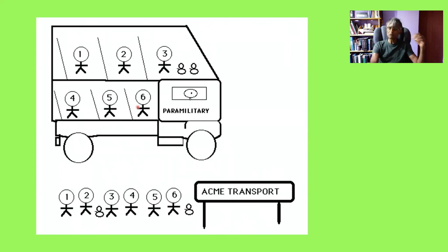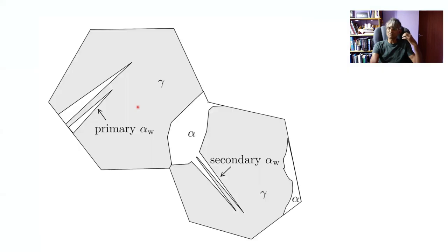And there are two specific morphologies associated with Widmanstätten ferrite. The first is this primary Widmanstätten ferrite. And notice that I'm drawing these as thin wedge shapes, and I'll explain that later. And they nucleate directly at the austenite grain boundaries and grow into one grain only, because after all, the change in crystal structure is achieved by a displacement. So you cannot sustain such displacements, choreographic movement of atoms across large crystallographic discontinuities such as grain boundaries. Okay. So primary Widmanstätten ferrite nucleates at an austenite grain boundary and then is limited to the grain in which